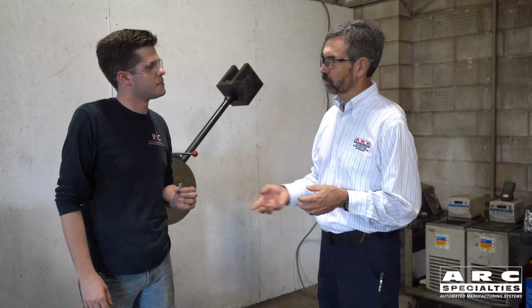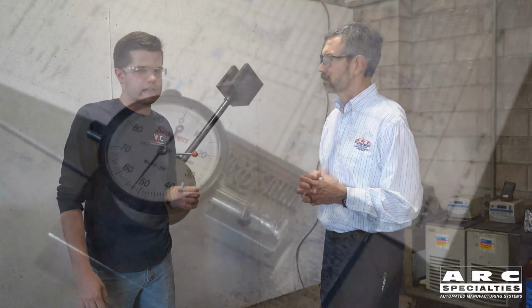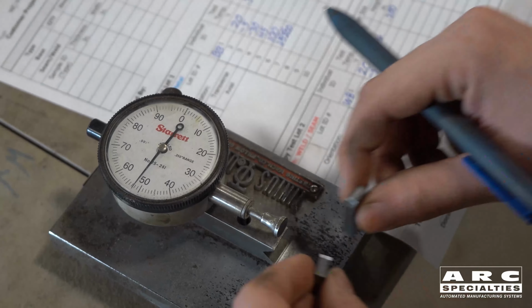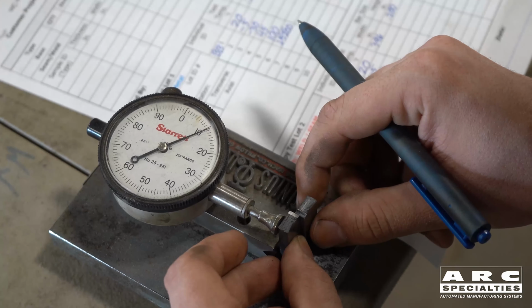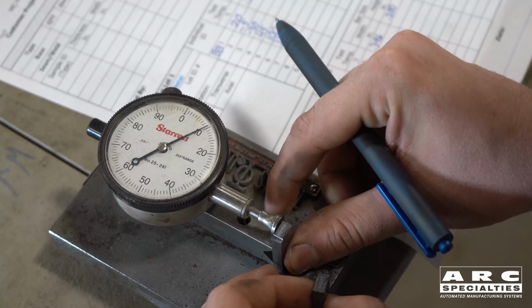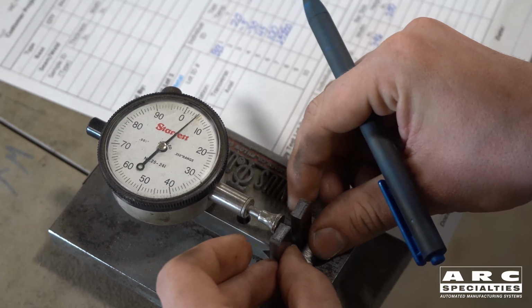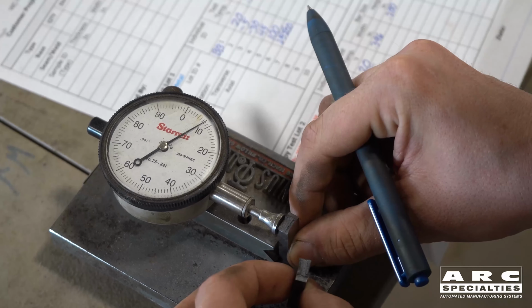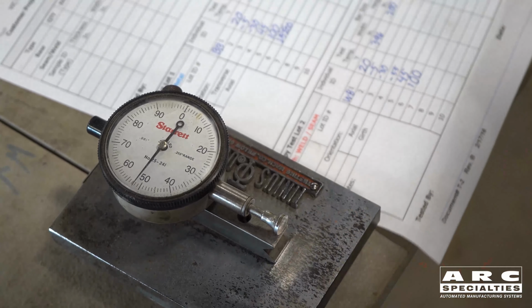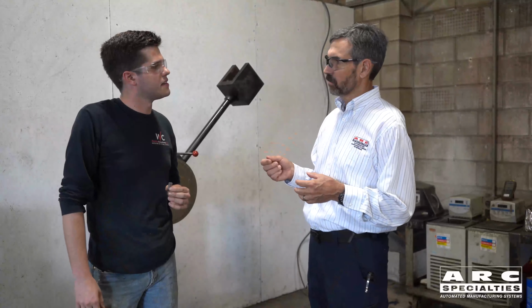And then what was the third inspection criteria you're talking about? It's called lateral expansion. And how do you measure this? Lateral expansion is measured with essentially a dial indicator, where we're measuring how much deformation the bar took when it was struck by the impact tester. The greater the deformation, the higher the toughness. That's correct.